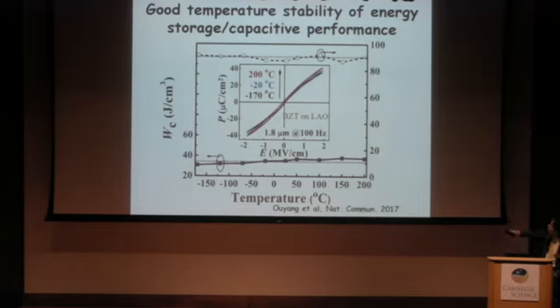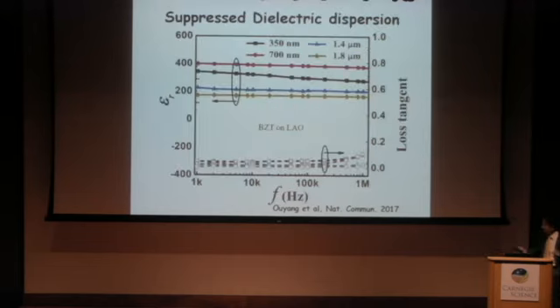We cooled down the film down to minus 170 and heat it up to 200 degrees C. You can see the energy change within about 10%. Efficiency, eventually, there's no change. It's all about 90%. And here's the dielectric dispersion. And you can see, very surprisingly, very stable dielectric constant. And we propose a mechanism of adaptive nanodomain. So the nanodomain can really respond to the field change when comparing with the large-scale domains.